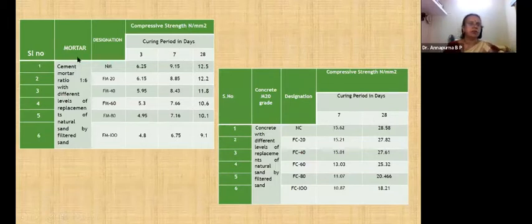Now the compressive strength for a mortar. The 1:6 mortar was tested here, and it is found that for normal sand, the compressive strength was 12.5. With the addition of filter sand, 20, 40, 60, 80%, the compressive strength reduced, and for 100% filter sand, the compressive strength of the mortar was 9.1.